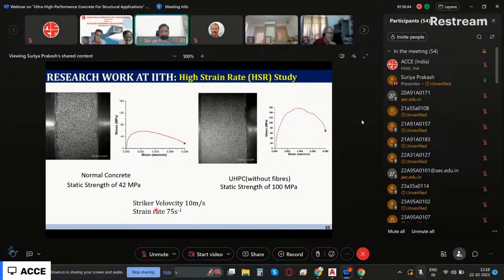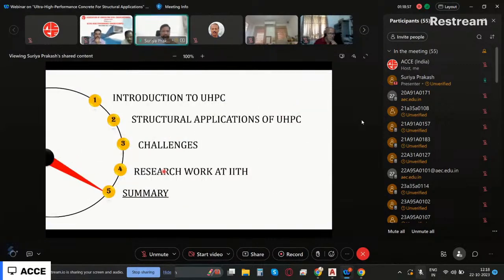We applied a striker velocity of 10 meters per second, corresponding to a strain rate of 75. So 75 is the strain rate. You see here the UHPC performed much better than normal concrete. So like that, we can see.